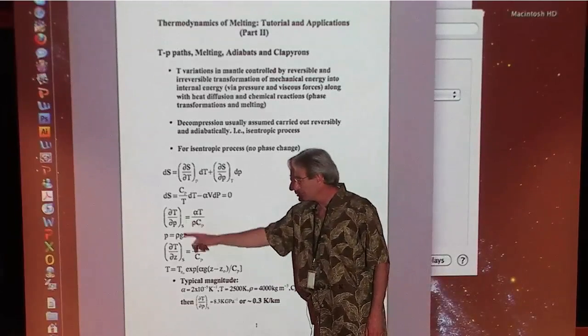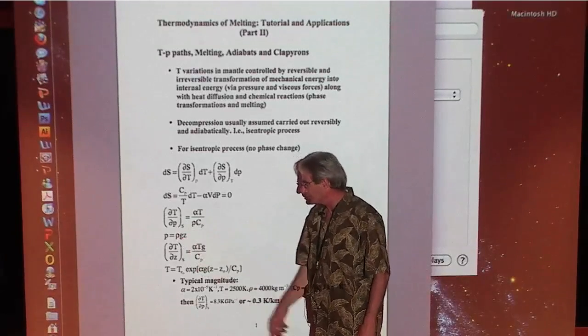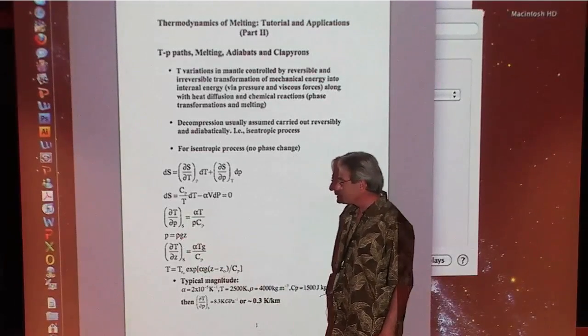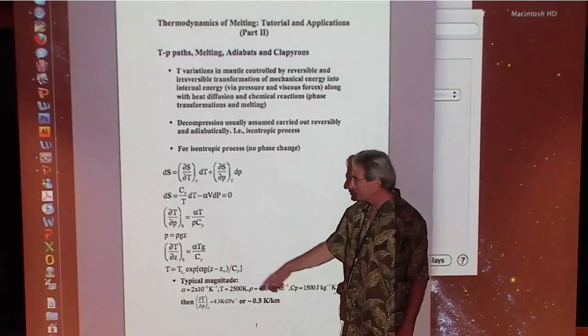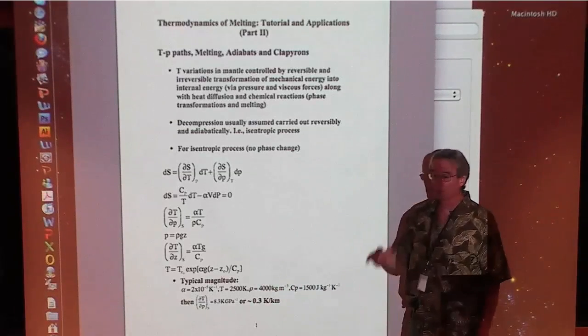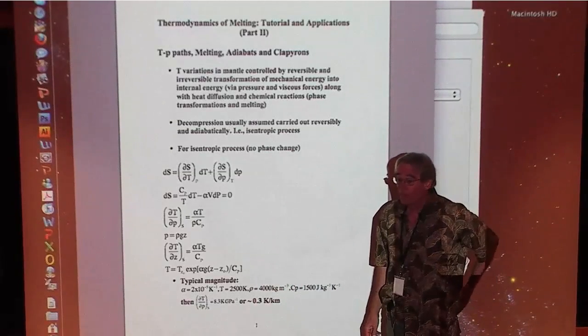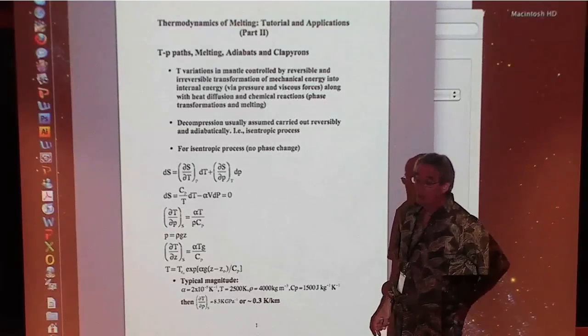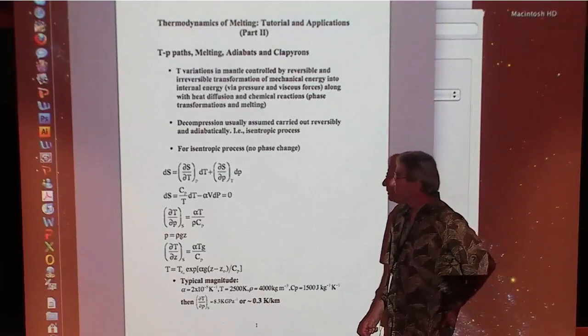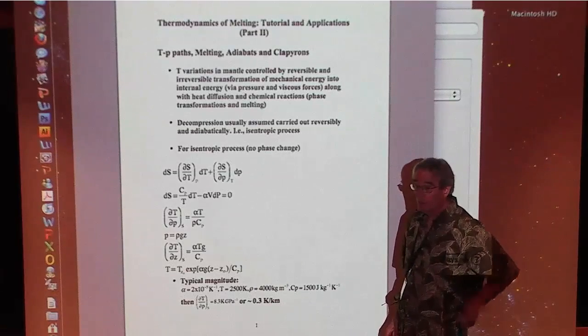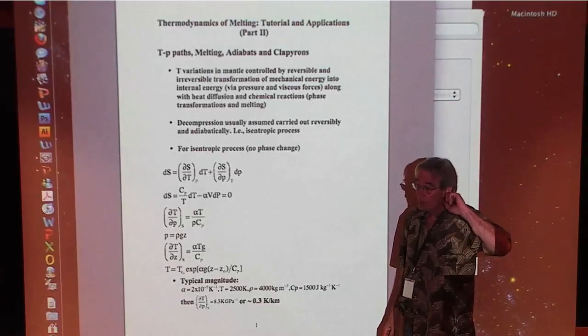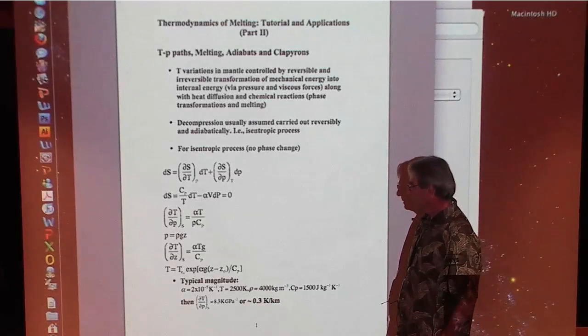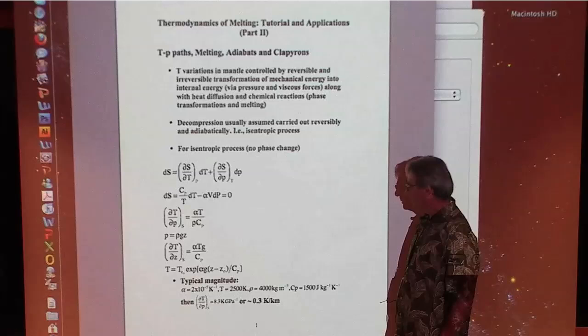And you relate pressure to depth, obviously, through something like that. And so then you end up writing dT/dz at constant S, looks like alpha T g over Cp. Yeah? Yeah, just going back to a previous question, if I had written that dT/dP_S equation, I would have put on an additional equal sign that would have said is also equal to the Grüneisen parameter times temperature divided by bulk modulus. So for the adiabat.